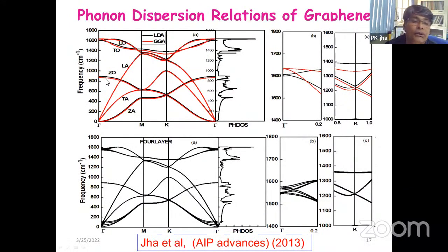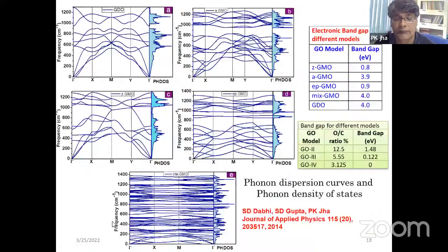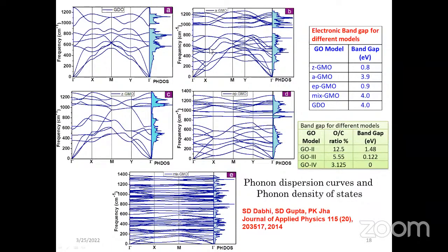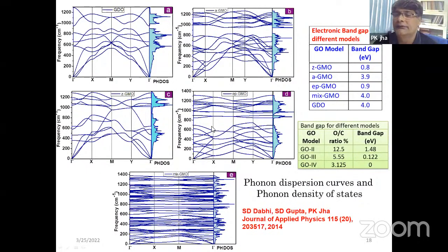You can see here this is the ZO and this is ZA, which is the out of plane acoustic mode and out of plane optical mode, right? This is for the single layer, this is for the 4 layer, and you can see that for the ZA, you have 4 different branches in the beginning. You can also tune the phonon dispersion curve of graphene by oxidizing it, right? These are all graphene oxide, and you can see there are different models for the graphene oxide. By having the ratio between carbon and oxygen, one can vary the band gap from 0.8 to 4 electron volt. So basically you can tune the phonon dispersion curve to get the phonon related properties of the material, right?